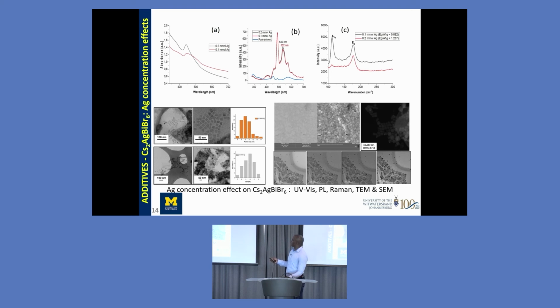But if you look into details with these advanced microscopic techniques, you can see that this is one of the big crystals. And if you look into detail, you see that it's made of small nanocrystals that are put together in a certain way to form that big crystal. And so if you expose those crystals to certain disturbance, in this specific case, we expose the nanocrystal to higher electron beam.